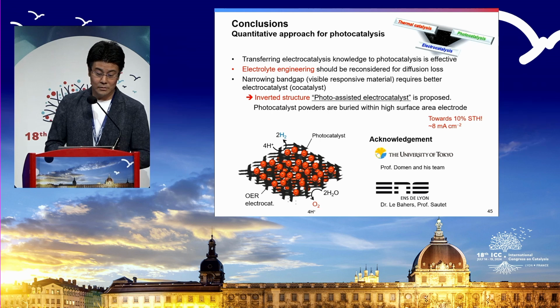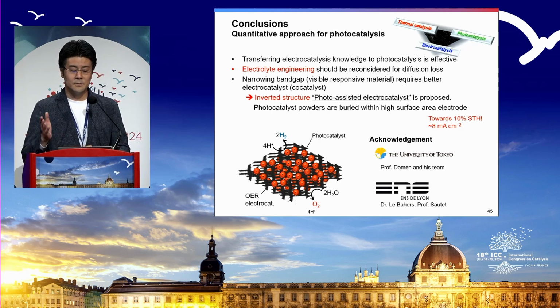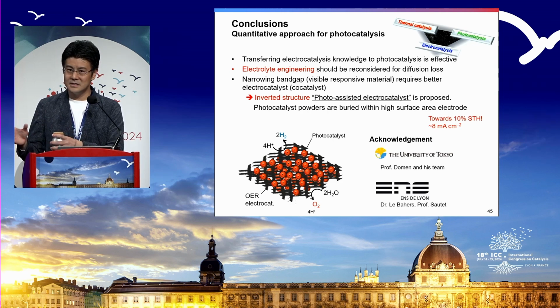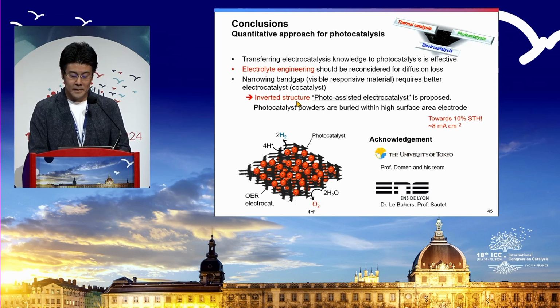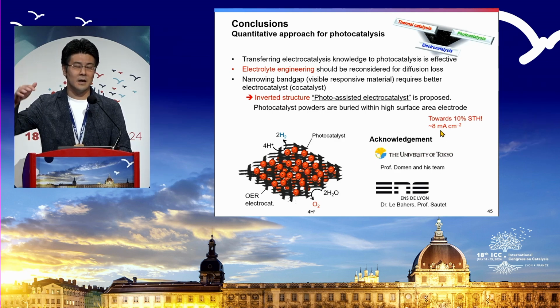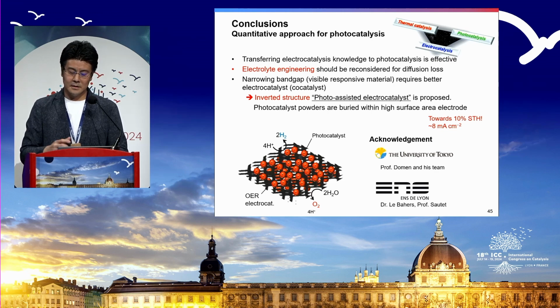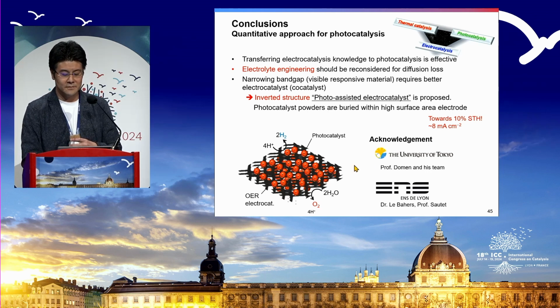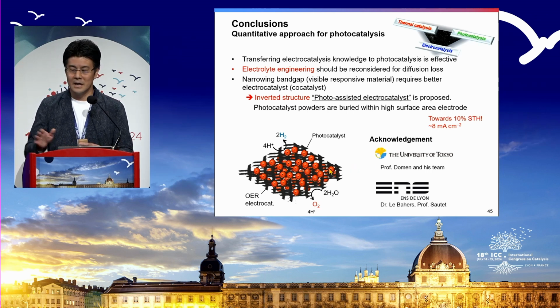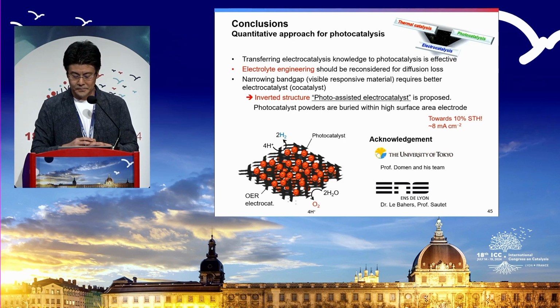So with this, I'd like to conclude. Transferring knowledge from electrochemistry to photocatalysis, I hope I convinced you that it's very effective. Electrolyte engineering, in particular cases in neutral conditions, is very efficient. Narrowing the band gap requires much more electrocatalysts together with it. And especially if you want to achieve 8 milliamperes per square centimeter, then probably we need to have much more electrocatalysts, so we propose this inverse structure for the photocatalyst sheet. And that can also be easy to expand, right? So you can put it in a larger scale.